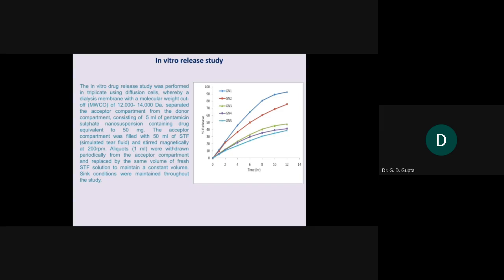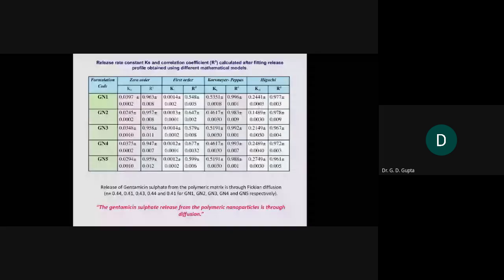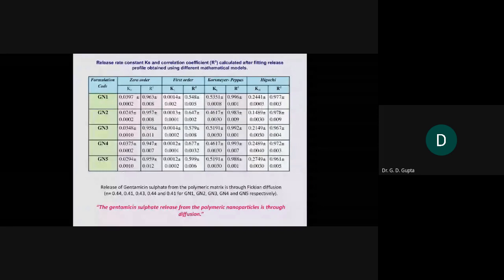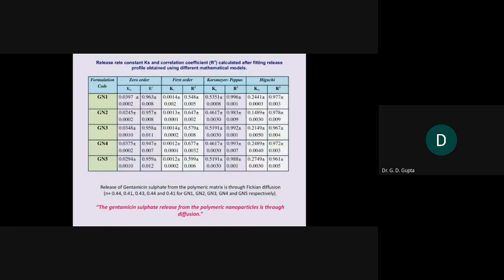Now, as far as the release kinetics is concerned, we can see this table, where we plotted the values into four models: zero order kinetics, first order kinetics, the Korsmeyer-Peppas equation, and Higuchi. The release of gentamicin sulfate from the polymeric matrix is through Fickian diffusion, because the regression R2 value of the Korsmeyer-Peppas equation is 0.99, 0.98, 0.99, whereas in Higuchi it is less than 0.99: 0.97, 0.97, 0.96. In zero order it is again 0.96, 0.95. First order it is again very low.